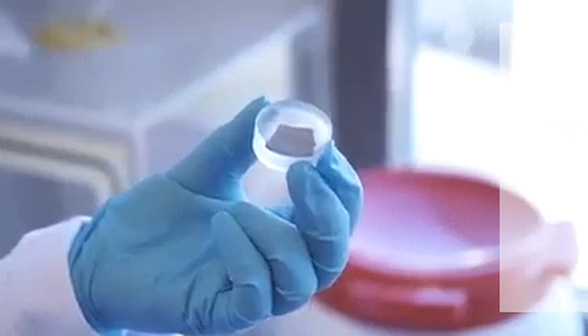We are going to prepare the resin. It's a mixture of 80% resin with 20% hardener. This resin is well mixed and sucked through the pipe to fill the molds. The amount of resin can be adjusted so that our samples have the same height, and we hold them some minutes under vacuum again. The resin hardens within 24 hours, and then it is possible to demold the samples.